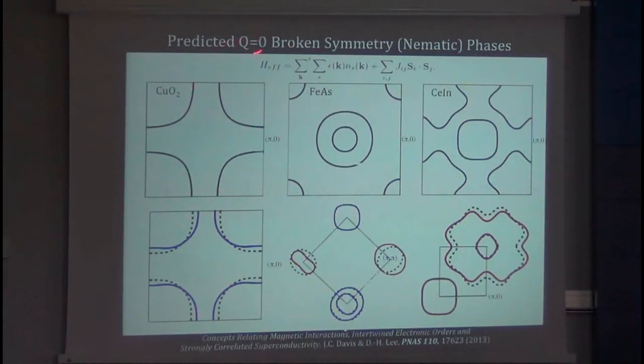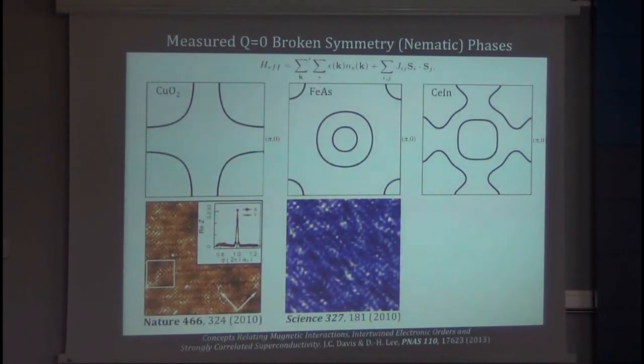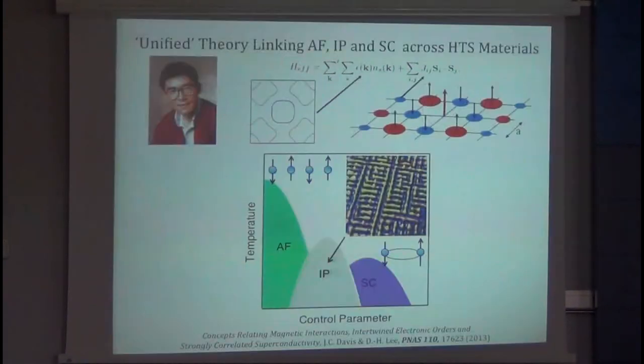Finally, one can predict the Q equals zero nematic phases, which should come from the same Hamiltonian. So one would predict for the cuprates that there's a broken C2 symmetry electronic structure. For the pnictides, that there's a C2 nematic electronic structure. And similarly, one for the heavy fermions like this. And two of those phases, the ones for the cuprates and the pnictides, are very well known to exist. Okay? So, in summary, you can take this Hamiltonian with a direct knowledge of the Fermi surface and the antiferromagnetism, and you can capture all of the known phases of these three families of compounds. And the credit for that achievement should go to D.-H. Lee.